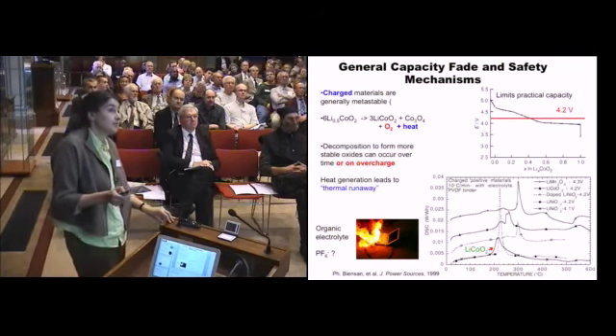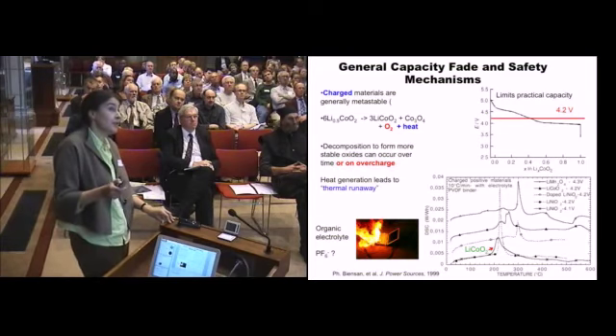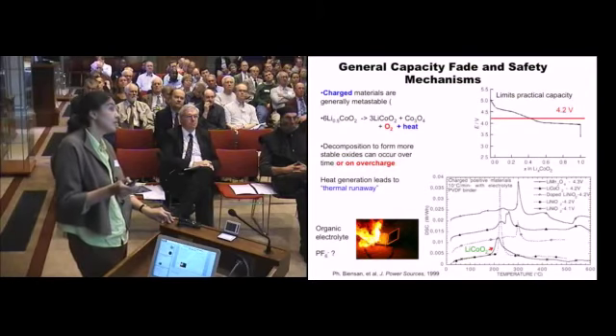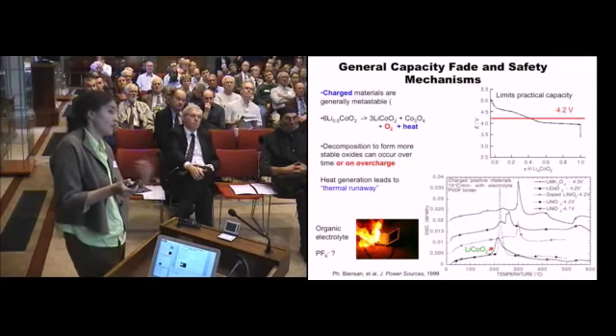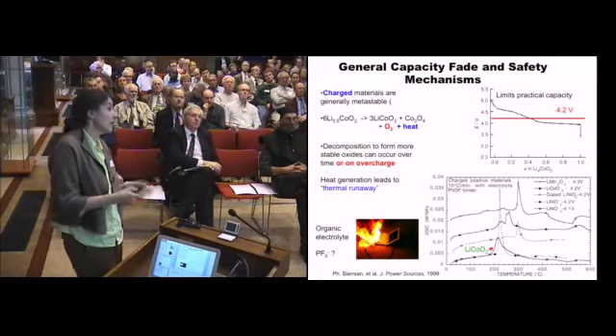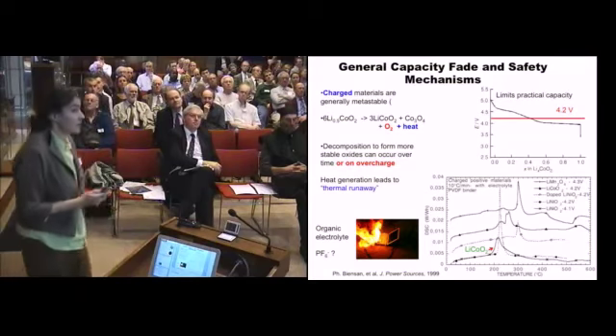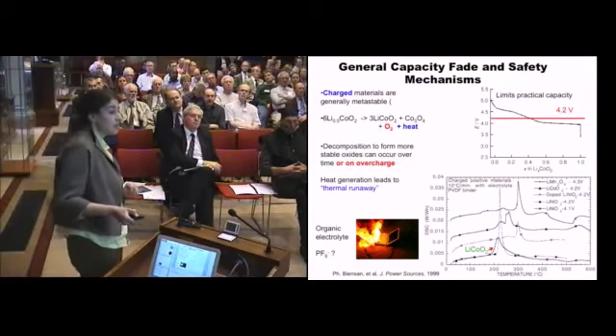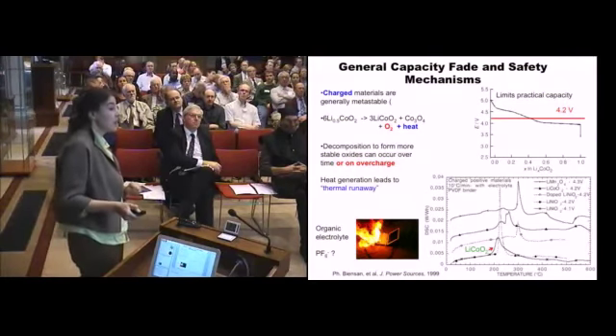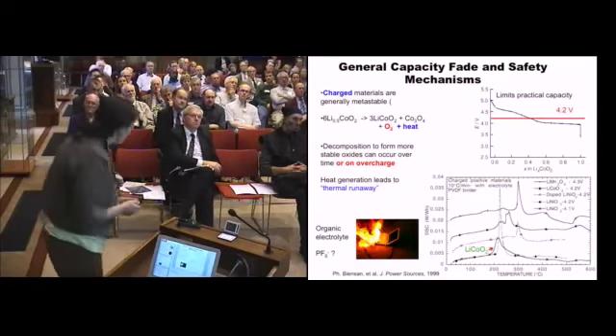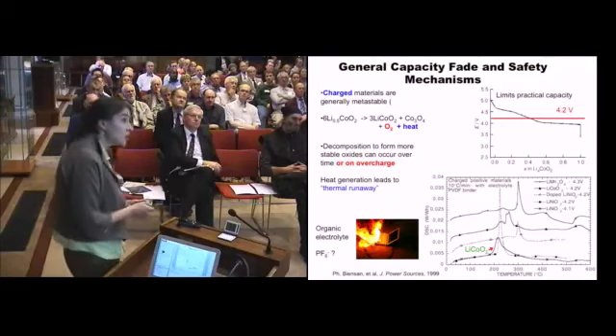And so what is often done is to limit the practical capacity to about 4.2 volts to stay in the regime where lithium cobalt oxide is more stable. And so that's the major reason, along with the structural transformations, why you just can't get the full amount of lithium out of lithium cobalt oxide. And so this is just showing you that if you heat a partially charged lithium cobalt oxide battery to above 200 degrees centigrade, it will decompose and give off oxygen.